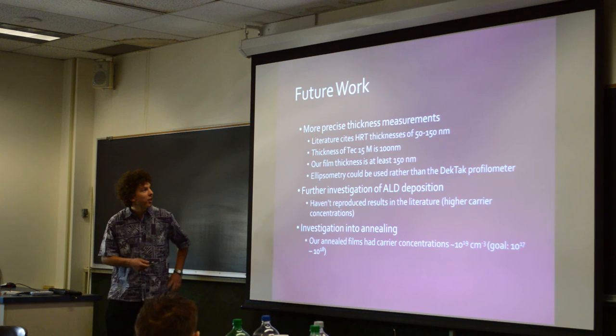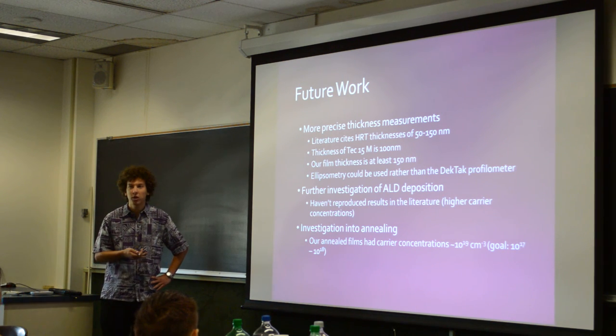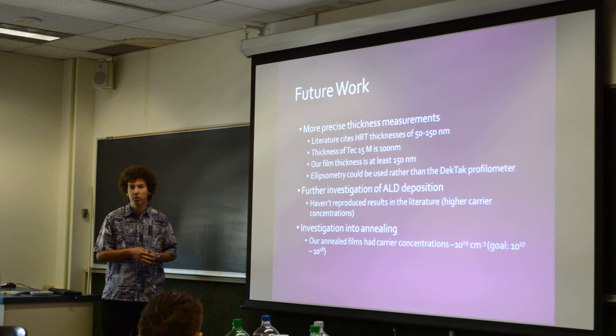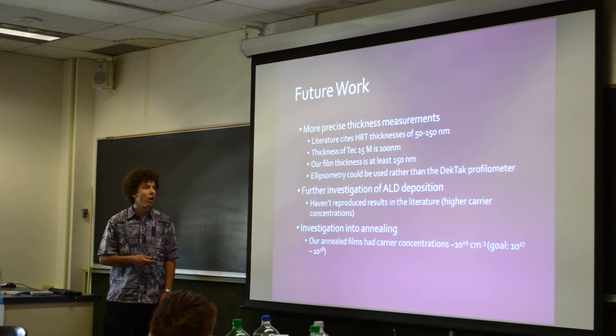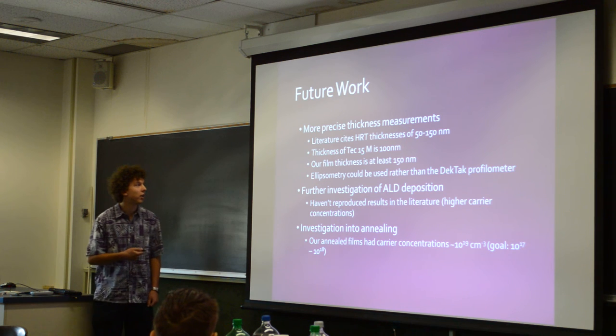In the future, I think one thing is we need more precise thickness measurements. We've been using a profilometer to do thickness measurements. And the tin oxide is very hard, so you scratch it with a razor blade and you're never sure if you're really going through it all or if you're taking some glass with it. So it's not a very exact way of doing things. And so I think that this definitely needs better precision on the thickness.